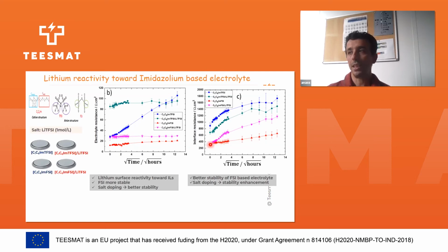What we can see is that we have different behavior of the interface resistance during time. I will not go into detail. I would just like to emphasize how we can link electrochemical information to XPS information. So the main conclusion here is that there is lithium surface reactivity toward ionic liquid in all cases, but this reactivity is less when we use FSI-based ionic liquid.